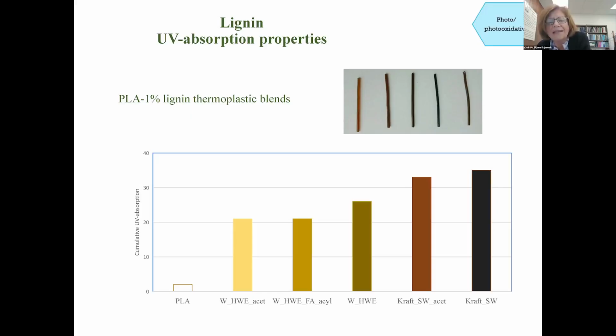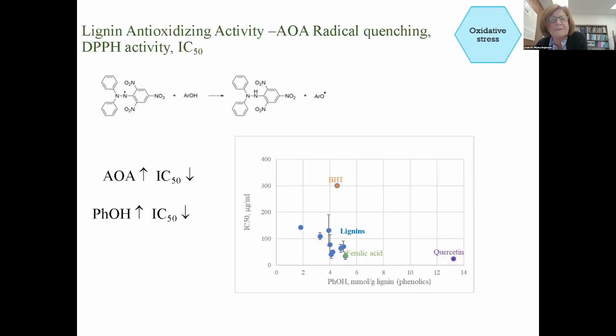We show here only at 1% lignin added to PLA, capacity of PLA to absorb UV light improves 20 times. You see on this slide, the different lignins can improve UV absorption different ways. Kraft lignin softwood is very powerful UV absorption agent.